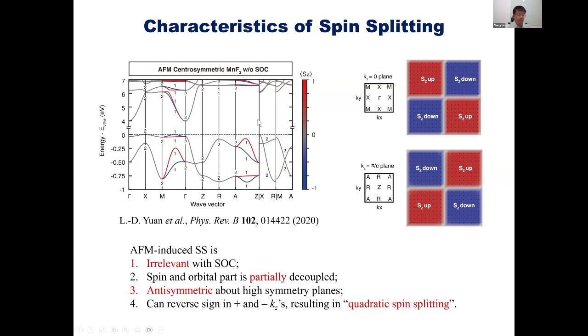So we have a lot of unique characteristics of such spin splitting. First, it is irrelevant to the presence of spin-orbit coupling. It is a non-relativistic effect that has an energy scale one order of magnitude larger than the SOC. Second, the spin and the orbital part are partially decoupled, as we mentioned before. Third, the calculations show that such spin splitting is anti-symmetric about the high symmetry planes in the Brillouin zone, having an alternating spin pattern. In manganese difluoride, we call this a plate-like spin texture. Fourth, in some of the spin-split antiferromagnets, the splitting can change sign between plus and minus Kz, forming a Hamiltonian that contains quadratic